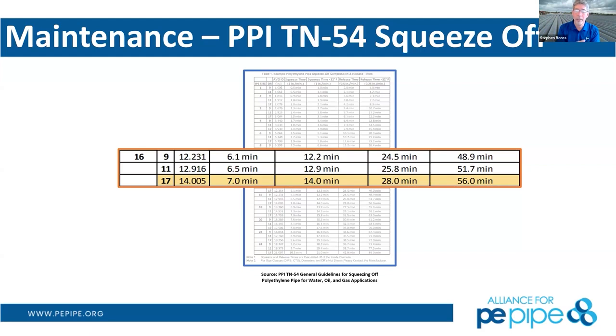You do your repair, put a tie-in in, whatever you need to do, and then you have to release that squeeze. The release is going to be slower than the compression. That is very, very key. This is when the damage could possibly be done. And then you have to go very slow to make sure the pipe is not damaged on the ID